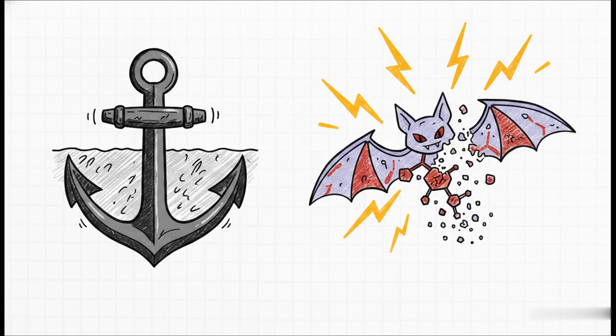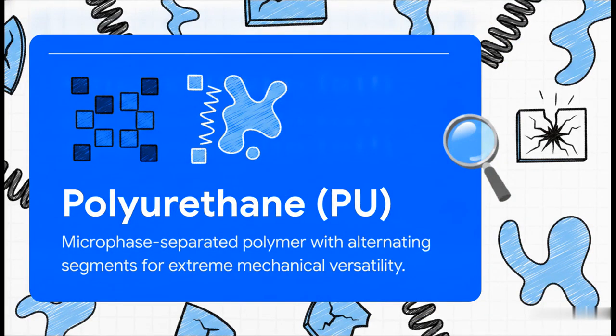Epoxy is essentially a vampire in sunlight. It has almost zero UV resistance. If you leave a pure epoxy coating outdoors, the sun's energy will completely shatter its molecular chains, causing it to yellow and chalk in under 6 months. That's exactly why epoxy is strictly confined to indoor use or buried as an unexposed base primer. Which brings us perfectly to family number 2.